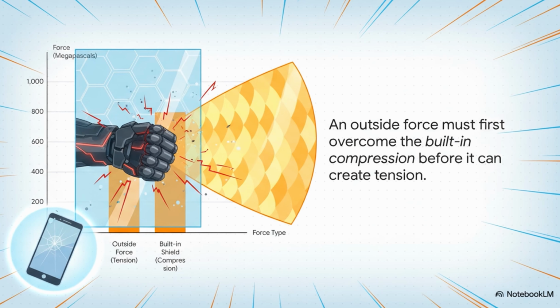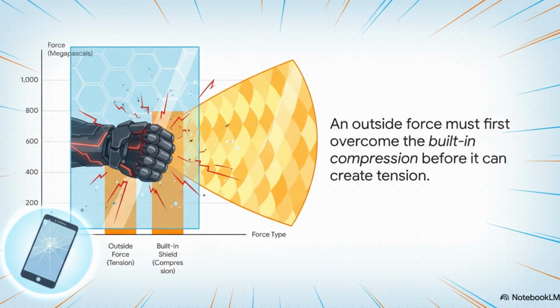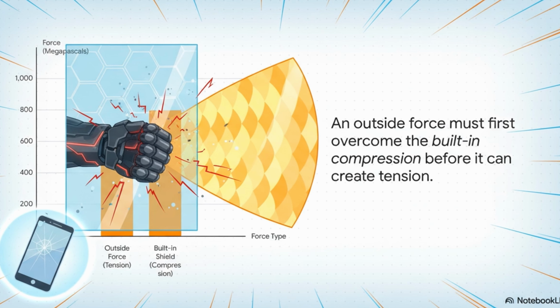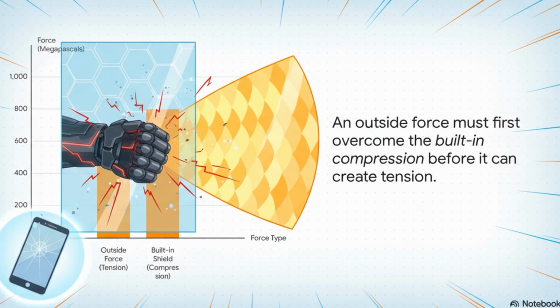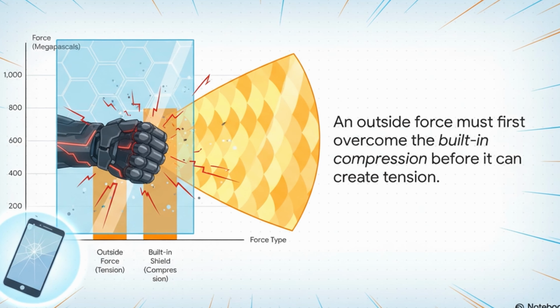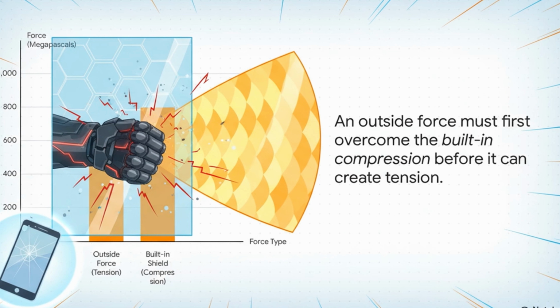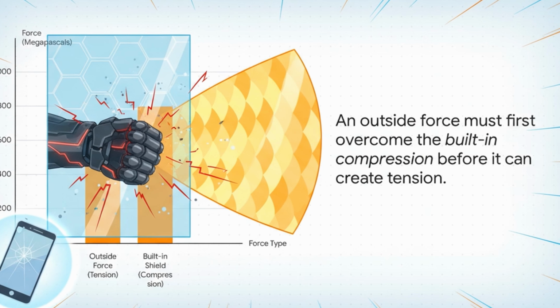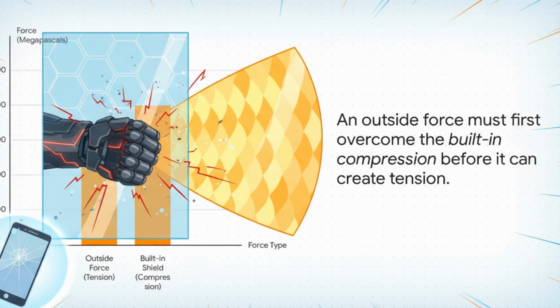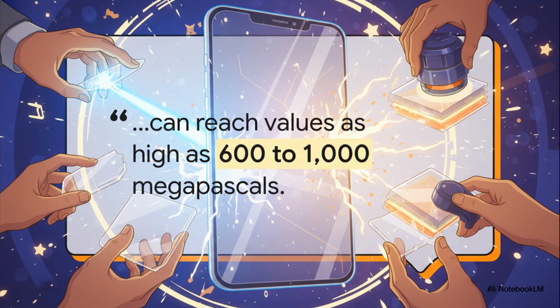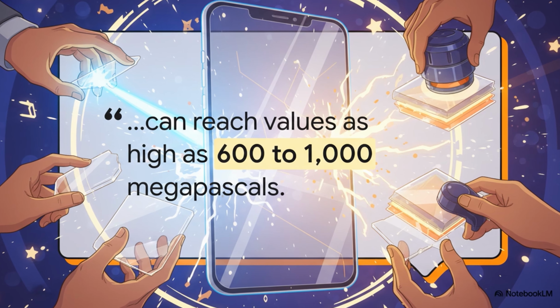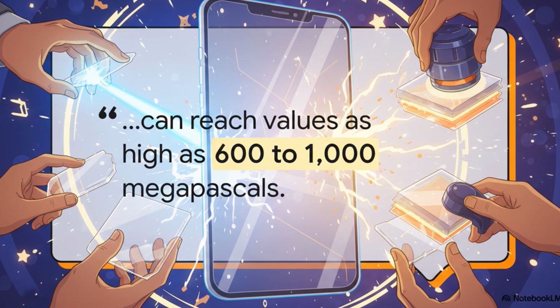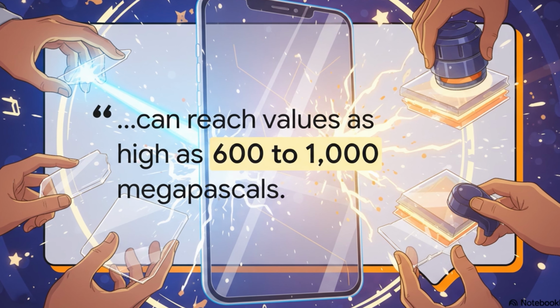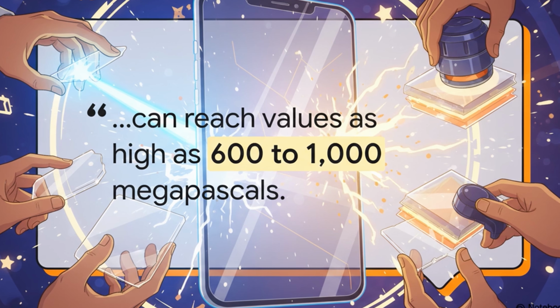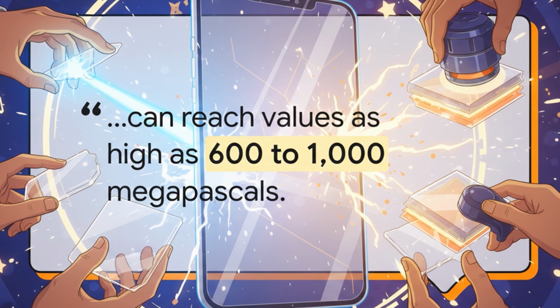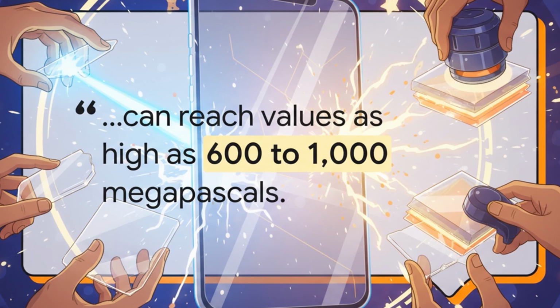It builds in this massive compressive shield that's always pushing outwards. So when an outside force, like you dropping your phone, tries to apply tension and pull the glass apart, it first has to fight against and completely cancel out all of that built-in compression. Only then can it even begin to put the glass into tension and actually cause any damage. And we are not talking about a small amount of force here. This compressive shield can be as high as 600 to 1,000 megapascals. To try and put that into perspective, that's up to 10,000 times the atmospheric pressure around us right now. That is a staggering amount of built-in protection.